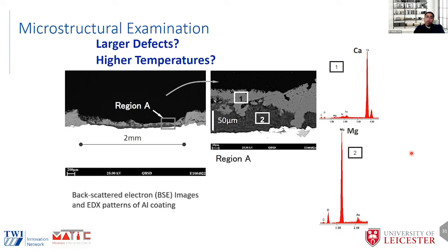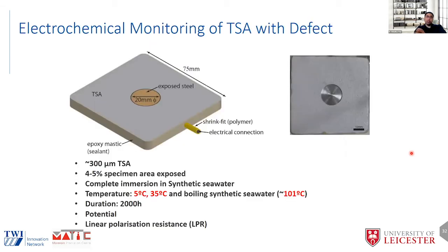We also wanted to look at what happens when you have larger defects and higher temperatures. So we did the same experiments, but with a more controlled defect area here, 20 millimeters in diameter. And we did the test at various temperatures. I'm going to talk about the 5-degree and boiling seawater in this presentation.